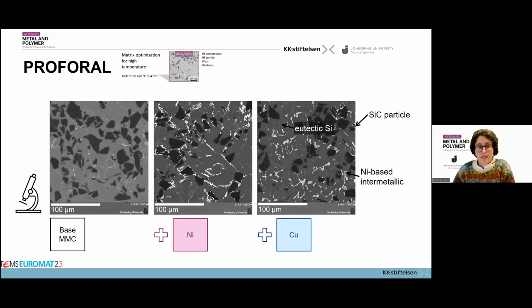So just to get familiar with the microstructure, what are we talking about in this case? If we go to the scanning electron microscope, this is what we would see. The base material appears with a light gray matrix, and that is the aluminum matrix. The dark polygonal features are the silicon carbide particles. So you see that they are quite polygonal and with sharp edges in the microstructure. You can clearly see them. The white parts here in the middle of the aluminum matrix are the eutectic silicon that comes from the matrix alloy. And these features will also be common to the other two materials.